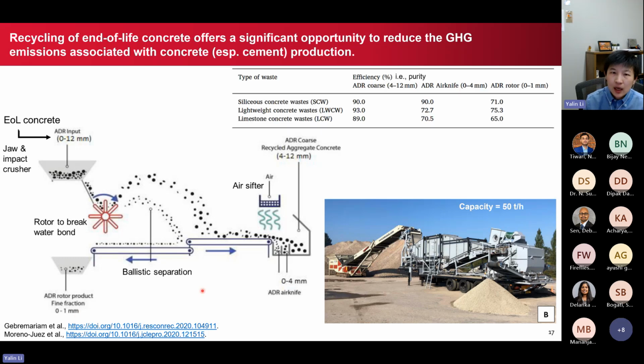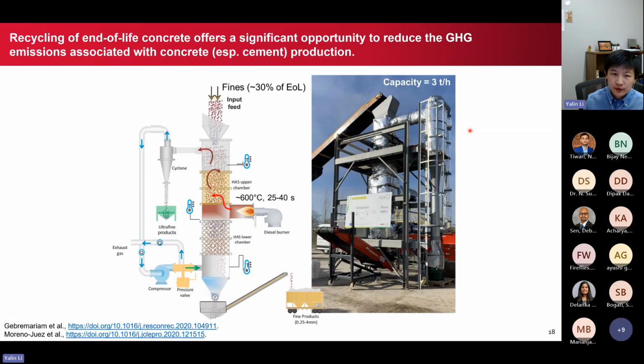So if we compare the purity of the products, you'll see this coarse product, they call it ADR coarse product, can be 90% plus pure, and this can be directly used as the coarse aggregates when you are remaking the concrete. And then the next 2 parts are not as pure, so that's why they have a further technology to purify that. Essentially they put the medium and the finest parts that come from the previous process into the next part, which further separates and purifies that into the fine products and ultra fine products.